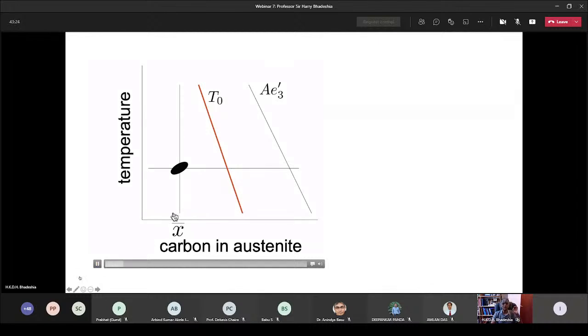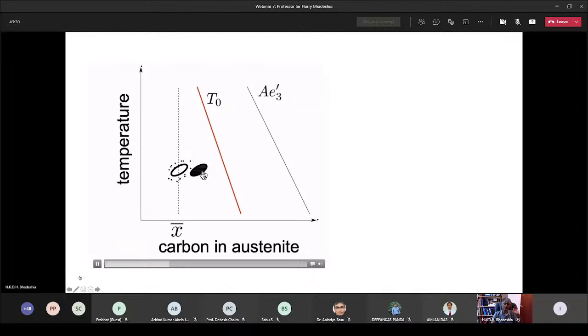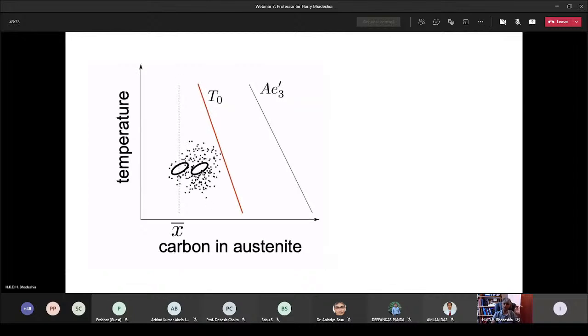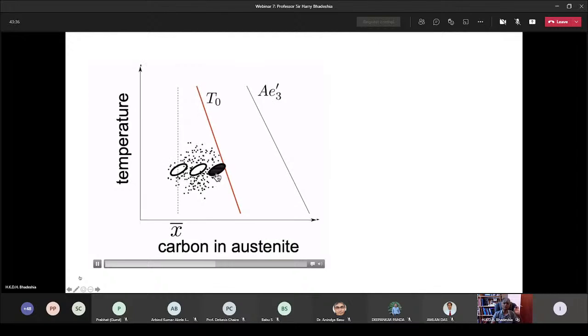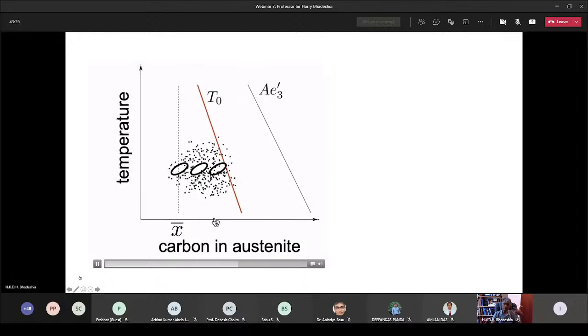Okay. But because we are at a high temperature, the carbon will partition into the remaining austenite. So the next plate has to form from carbon-enriched austenite, and then it too partitions carbon. And the third plate is forming from even more enriched austenite, and it partitions carbon. And beyond this point, you cannot get any bainite transformation. Okay, so this is a really important point which we'll use in designing really nice steels. So the T0 curve is the point where the bainite reaction will stop, and the composition of the austenite that remains will be defined by this T0 boundary.